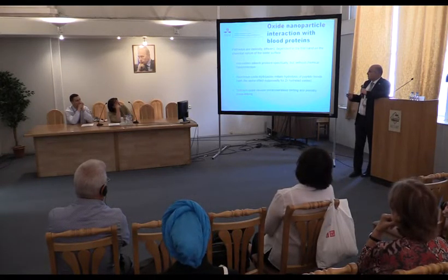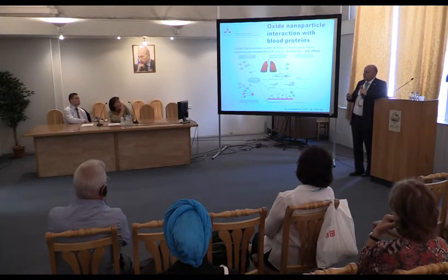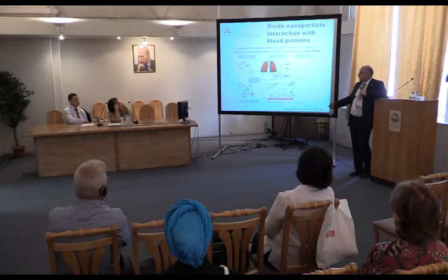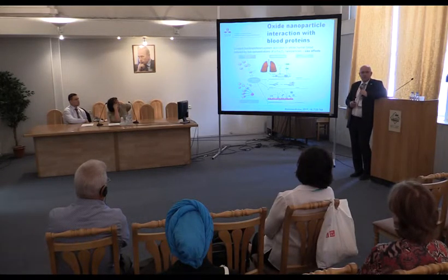So we have looked closer at this case, and of course size and shape of the particles also play a role, but I don't have time to look more closely at this. What we were able to see is that there are, of course, some effects of size and shape. So if we have big particles, then it is the complement system which is activated. And the complement system is like the primary immune response in blood. It is recognition of foreign bodies in the blood. So in this case, inflammation starts.